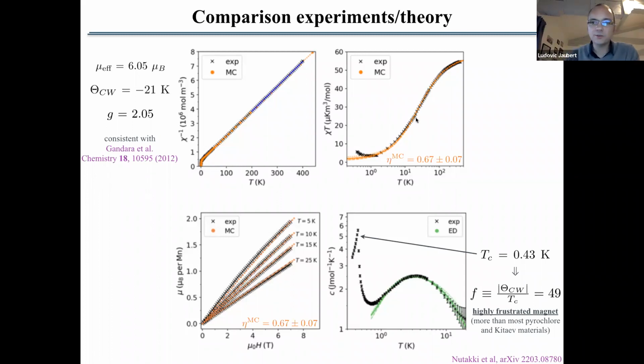And when we compared simulations to experiments, both in the field or in the susceptibility, we find a very good agreement down to roughly 1 Kelvin or a little bit below for a value of eta. So eta is J2 divided by J1, that's the ratio of the two interaction matrix of roughly 0.67. And this value of 0.67 compares very well with DFT estimate of 0.69. So both magnetic measurements compared to simulations and DFT ab initio calculations give us the same ratio of J2 over J1 for this material of MnTa2.